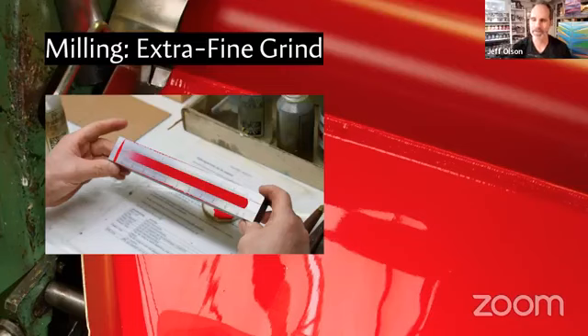It's caught in this big vat and then poured through again. Each time the gap between the rolls is reduced. You can't do it all at once. Some of the pigments are very hard and they can damage the rollers if you try to do too much too quickly. So to get the pigments ground down very finely, you have to put them through the mill a lot. And so this contributes to the cost. Artist grade paints cost more, not only because of how much pigment is in them, but also because of how long they are ground for.